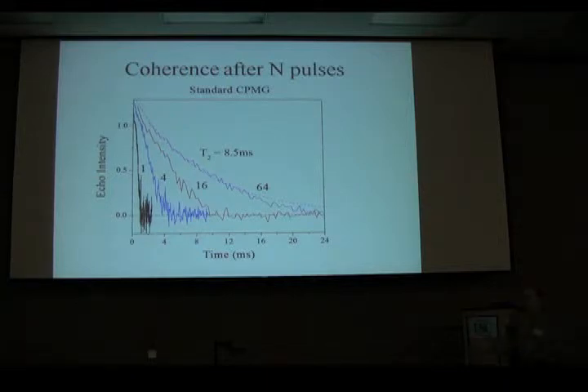So now what I'm going to do is compare some of these sequences. The CP isn't particularly interesting because that Carr Purcell where everything was X. It all just died away too quickly. Here is a standard CPMG. And you can see this is with one pulse. So this is just a Hahn echo. Now if you put in 4 things get a little longer. 16 it's getting a little longer. And that spectrum there with 64 you can see we're getting pretty much a good echo. In fact we're pretty sure that this would actually get from some other data. We haven't tried it with 128 pulses yet. But we're pretty sure it will get longer. You can see this is an exponential fit with a T2 of 8.5 milliseconds. And you can see it's deviating down here. What that says is I think that at long times we're still getting this magnetic field noise. We haven't completely decoupled it with in this case 64 pulses.